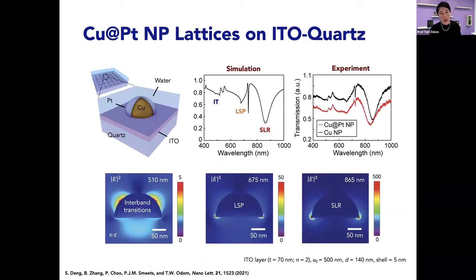So we initially wanted to test just the photocatalytic properties of these arrays, but we found out we didn't have enough sensitivity in our detector to measure the hydrogen that was being evolved. So then we decided to measure the photo-electrocatalytic properties. So what this meant is we needed to put these arrays on a conducting substrate. And in this case, we put them on indium tin oxide because it's conducting and transparent, but it also has a high index. And so we needed to do some modeling to be able to see where do the resonances of the SLR occur, where is the localized surface plasmon, and where are these interband transitions.